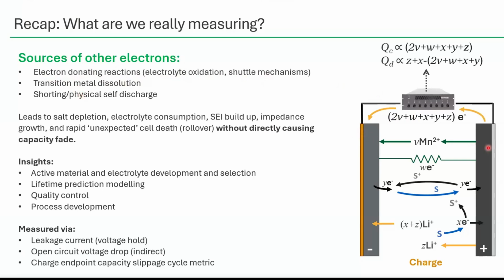So looking at this diagram here, we have things like transition metal dissolution, where we're shuttling charge across the cell, and to create charge balance, we actually have to pass current through the external circuit, and we're counting these electrons. With a short circuit, the same thing is happening. As we're trying to charge the cell, there's this internal self-discharge, and we're counting all of these excess electrons.